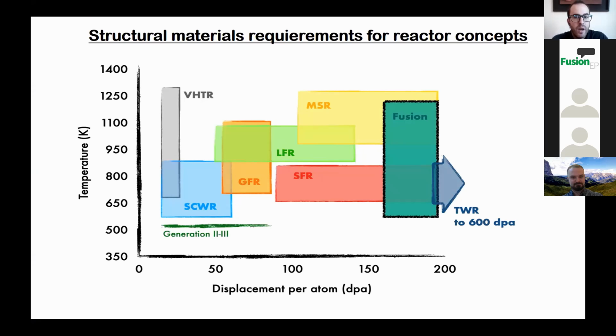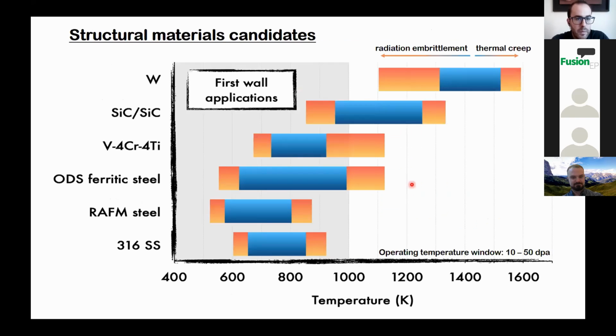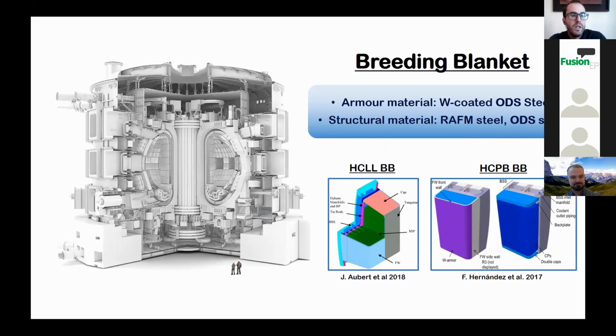To allow operation at much higher temperatures than today's, advanced reactor concepts are being developed. Within Generation 4 concepts for fission reactors, nuclear fusion reactors lie at the highest standards with an unprecedented combination of temperature, radiation dose, stress, and coolant compatibilities. Thermal creep at higher temperatures and radiation dose, and radiation embrittlement at lower ones, will limit structural material application. ODS steels and tungsten alloys are desired as structural and plasma-facing materials at the moment. Eurofer 97, as a reduced activation ferritic martensitic steel, is the structural candidate for ITER. First wall components are currently being developed.